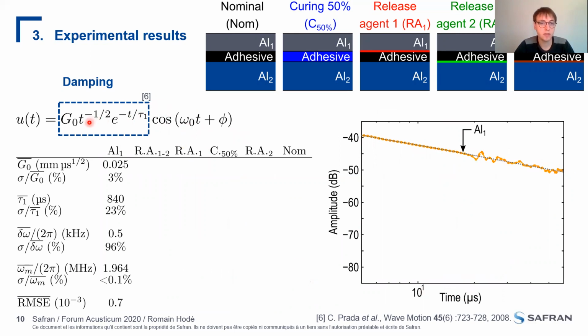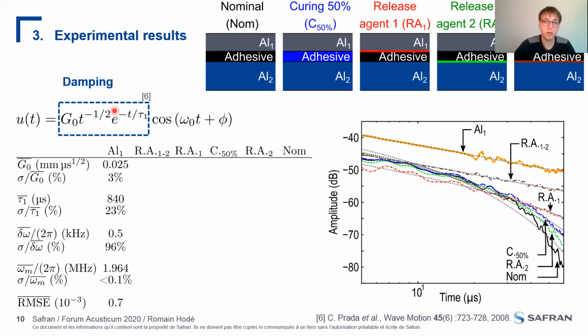And we can see that this attenuation is a function of the time and also of the parameter τ1, which is due to viscoelastic effect. But in this case of an aluminum plate, this parameter is really high. That's why we have mostly an attenuation as a function of time. But when we want to apply this model on the other curves, we can see that we have some discrepancy, notably for the nominal case.